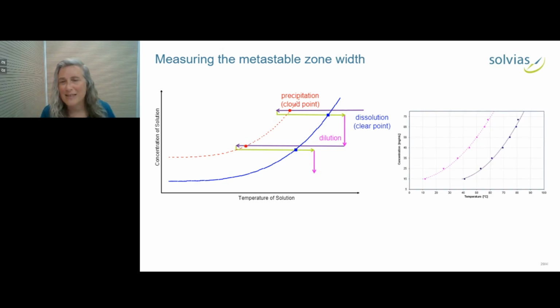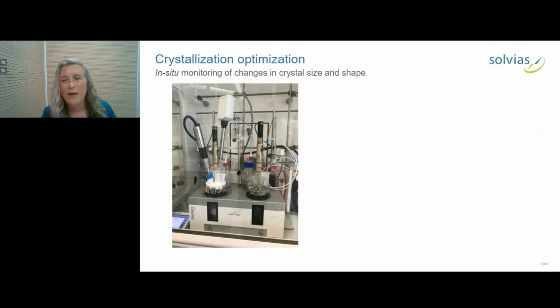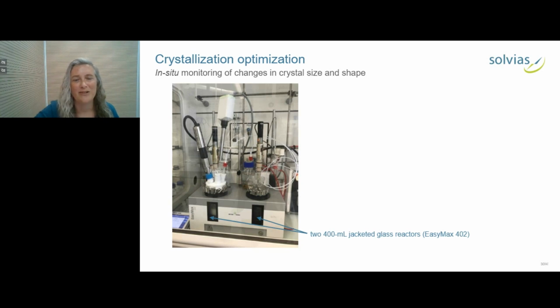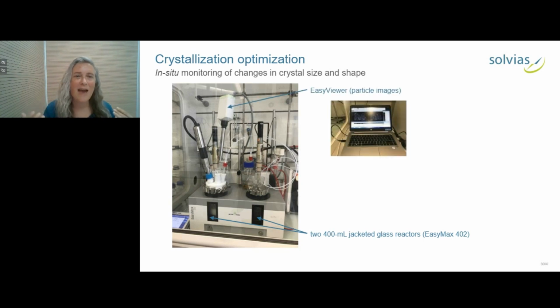And on the right here is an example of just a customer's real system where we did one of these metastable zone width measurements, and you can see the solubility and the metastable limit. This was about a 25-degree width to the curve, so that gives us quite a bit of room to develop a robust crystallization process. The tools that we would use for such a process are shown here. We have other scales as well, but here are two 400 milliliter jacketed glass reactors, and we have some probes,